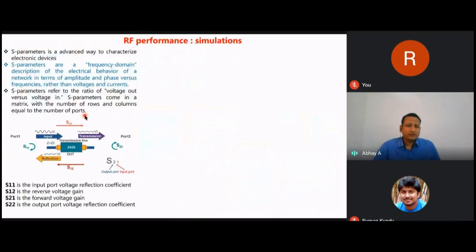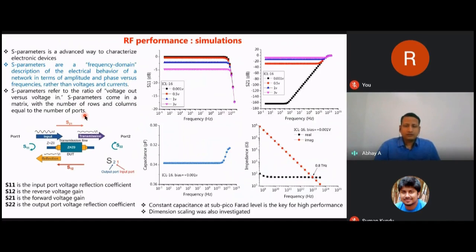So these devices were measured for AC, and the measurement is called S parameter measurements. These S parameters were first simulated using the TCAD, and when we collect the data for port 1, S11 is this one. So this is the input wave and the reflected wave, and this data is called S11. And when we plot it here, you can see this black line, which is at zero bias. This line is completely flat, and it is even flat at 100 gigahertz.